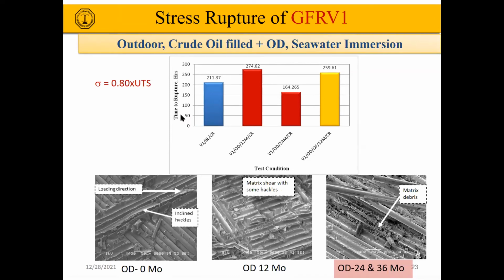We have here the time to rupture, that is the stress rupture of GFR-V. We have observed almost the same trend where after 12 months, you have the rupture time higher than that of the baseline received after 24 months. But here there is so much scatter in the results that we believe that this is just the average, that it would continue also to increase after 24 months. The oil field also showed the same trend as for the tensile test specimens. And these are the fractographs. We can see that after 24 and 36 months, we start having decomposition of the matrix.